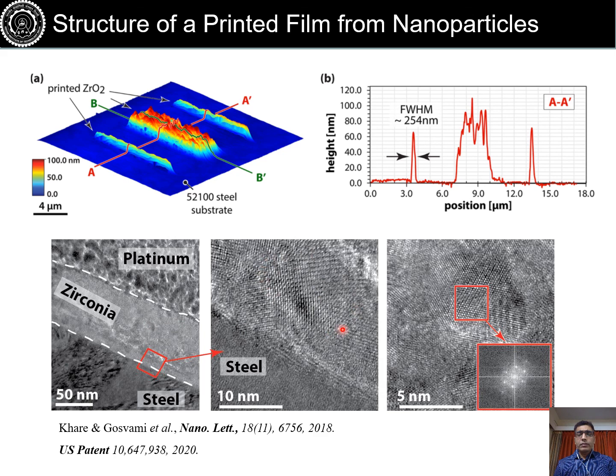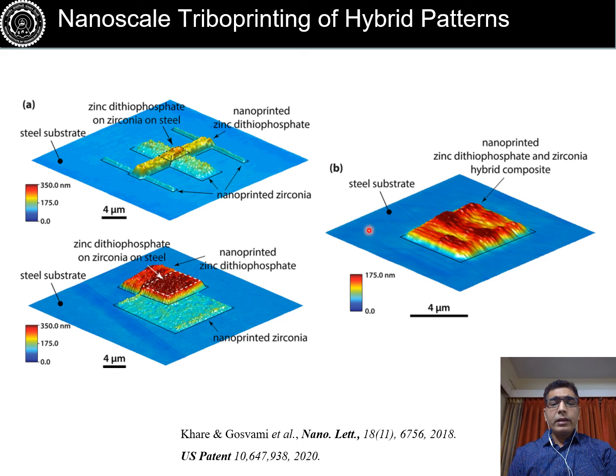And we see that the film has developed a highly crystalline structure. It's a polycrystalline film, so very dense. We also did nano indentation and other mechanical property measurement, and we found that this film is very robust, close to mechanical properties of bulk zirconia. And then we also try to play around with mixing these nanoparticles with molecular reactive molecules such as ZDDP. So we can do either layer by layer patterning, or we can do a kind of composite coating where we mix nanoparticles and the reactive molecules together, and then we co-deposit these structures. So all sorts of patterning is possible by